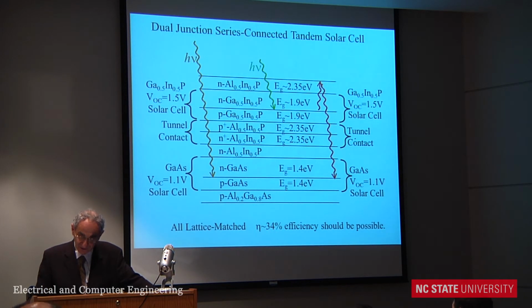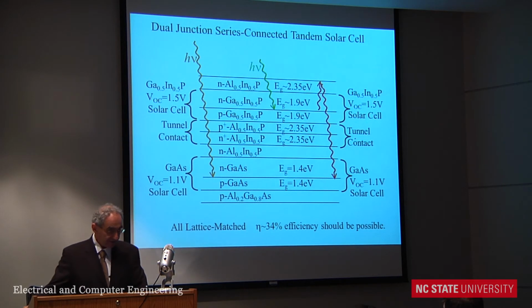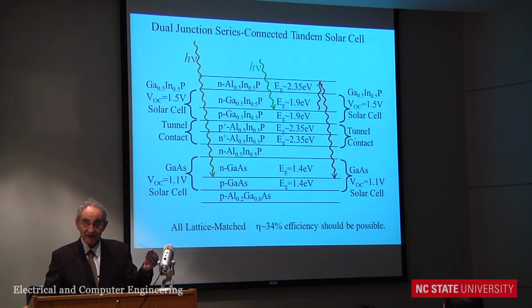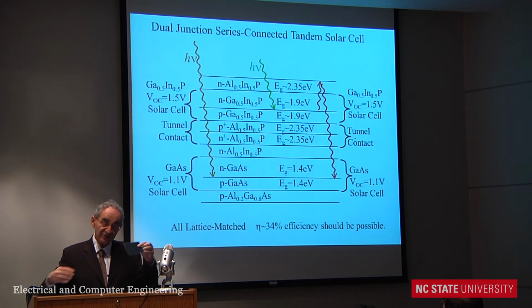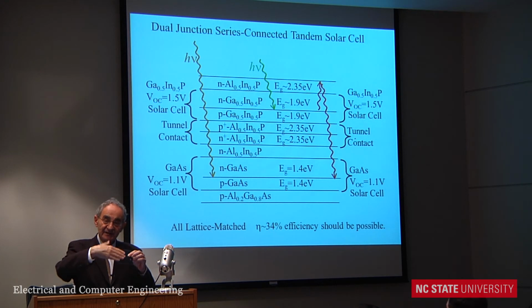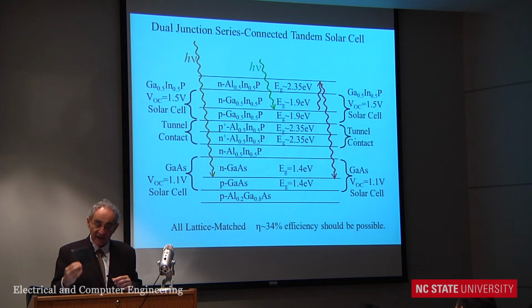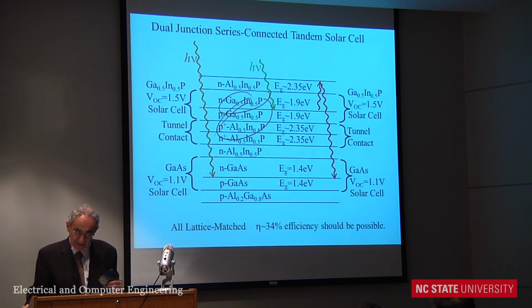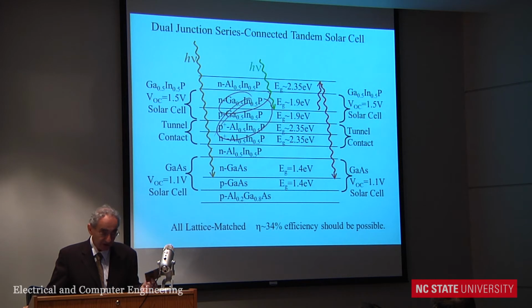You do need luminescence. Okay, so what about tandem solar cells? Of course, in the future, we're all going to have tandem solar cells. Because why stop at 28.8% efficiency? So in this same film, at Alta Devices, they simply grew another couple of layers of indium gallium phosphide. They were already using that compound as a window on the solar cell anyway, so there's no added complexity to add a second junction. They added a second junction with indium gallium phosphide, and they made a dual junction. So it looks just like this.